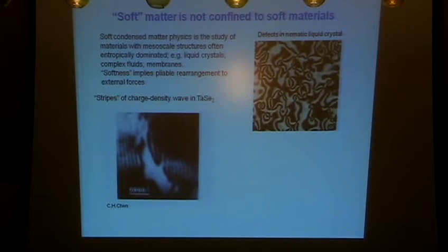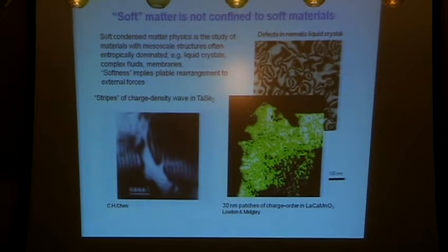But nonetheless, we've known for a long time that you can take these charge ordered structures and manipulate them and play with them and change the patterns. And one of the ones that I do want to talk about is a sort of classic manganite, lanthanum, calcium, manganese oxide, where what you're looking at here is a picture on a length scale of 100 nanometers, and the white dots here, around 30 nanometers, are charge-ordered insulating pieces of lanthanum, calcium, manganite, and the black bits, which are in between, are actually ferromagnetic metal. And so this is stuff which actually contains, in something which is nominally chemically homogeneous, two phases.